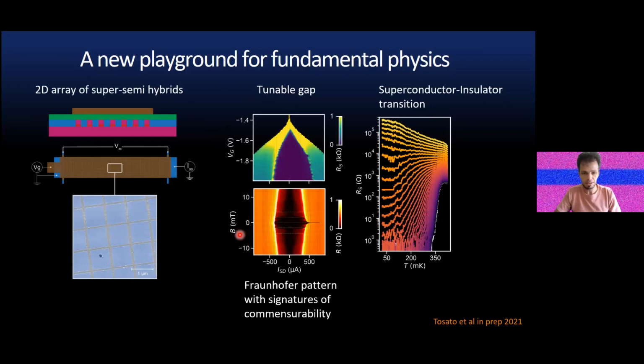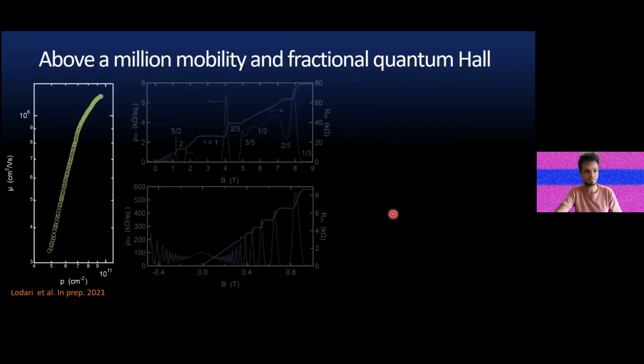And if you turn on the magnetic field, you see a typical Fraunhofer pattern, but you also see some other features here that line up. These are a signature of commensurability due to the fact that you have many islands here. And the nice thing is that we see this transition where, depending on gate and temperature, you can really go from a superconductor to an insulator via a metallic state. And there's a lot of debate in the literature about this phenomenon. So this is to say that this technology is really open for a lot of applications.